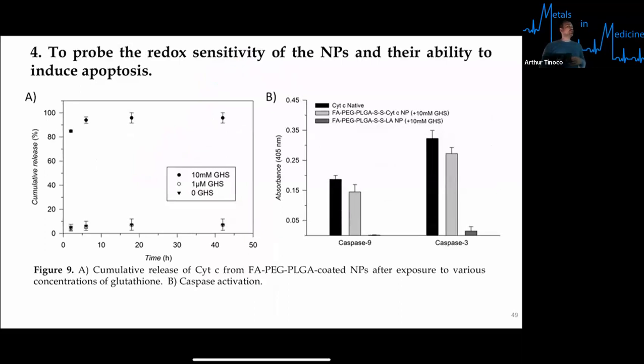All right. So here we're looking at the functionality of this. As I was mentioning to you, you want to be able to release the cytochrome C from the way you've designed this. So the idea is to probe how the redox environment of the cells can influence this. Here we're looking at the use of glutathione as a model of the redox environment of the cell. So we're not looking at this within the cellular environment. We're simply looking at how different concentrations of glutathione can potentially lead to the release of cytochrome C. So we're tracking release of cytochrome C in the presence of no glutathione, 1 micromolar glutathione, and 10 millimolar glutathione. In our blood, we have about micromolar amounts of glutathione, and in our cellular environments, we have 10 millimolar, and actually even higher in a cancer cell.